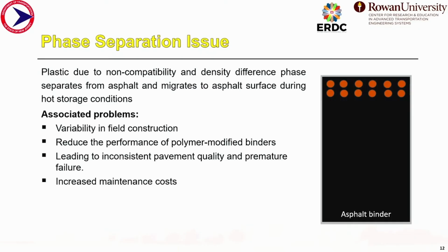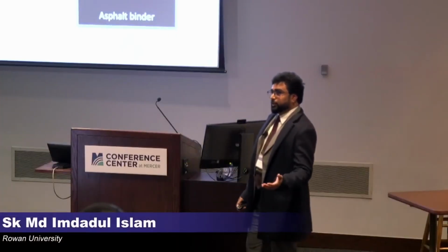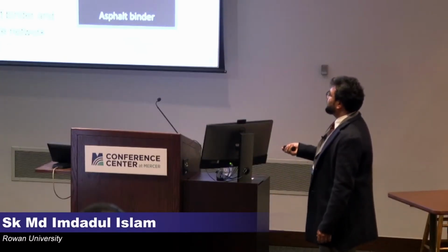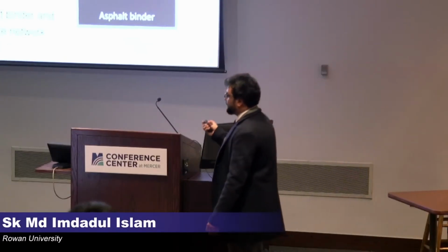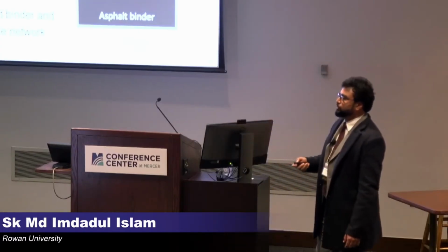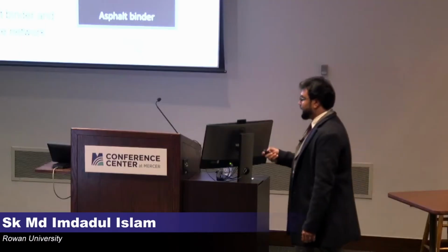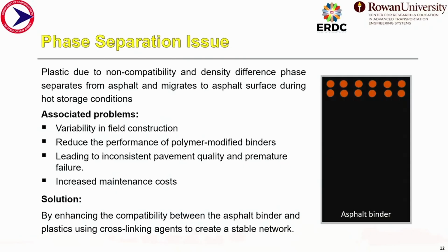And what problems do we face if there is a phase separated plastic modified asphalt binder? First, there will obviously be variability in the field construction. It will not be a homogeneous modified binder, which will eventually reduce the performance of the plastic modified binders, leading to inconsistent pavement quality, and then we will have premature failure and higher maintenance cost. So the solution is, as we have to care about this phase separation issue if we want to proceed with the wet mixing method, enhancing the compatibility between the plastics and the asphalt binder with a cross-linking agent to create a homogeneous asphalt binder matrix.